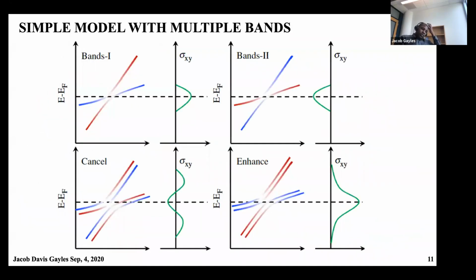So now we talked about this intrinsic, so we're going to focus mostly on this intrinsic for the rest of the talk. We want to show some simple models of what gives rise to this anomalous Hall effect, and this is usually when you have some band inversion with spin-orbit coupling and an internal magnetic field from some magnetization. And so for two simple bands, this gives you anomalous Hall effect, and once you change the chirality or inverse the magnetization, you can inverse the anomalous Hall conductivity. And this is quite known, we'll go through this more.